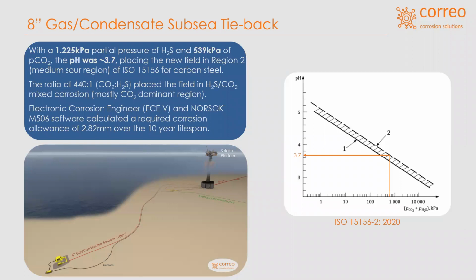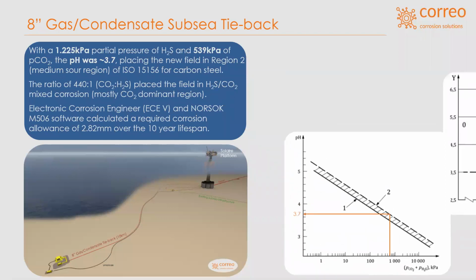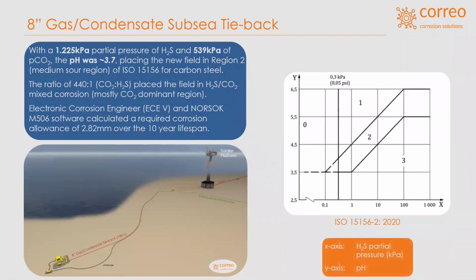So when we add these together using ISO 15156, we then came with a pH of 3.7, which then had us landed in the sour region 2, which meant that this would be a medium sour, and we would have to then assess this for our material selection. The partial pressure ratio of CO2 to H2S was 440 to 1, which meant that it was in the mixed corrosion regime, but predominantly CO2.